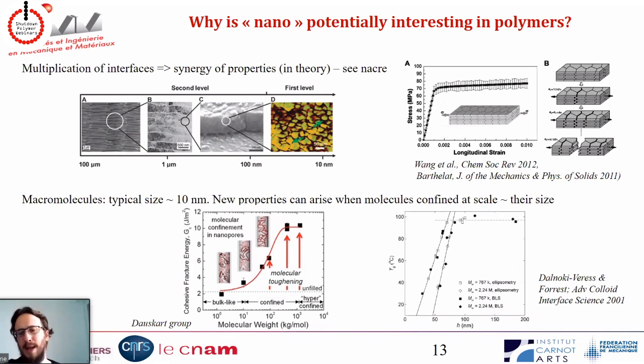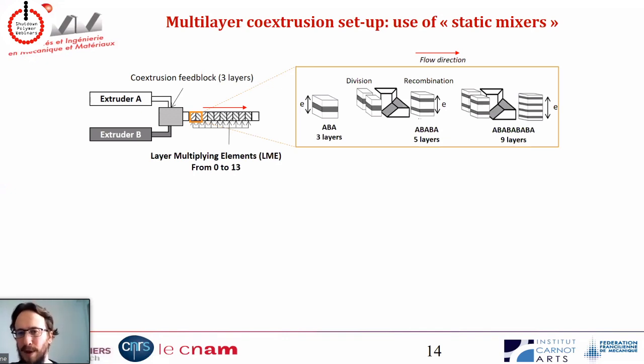nanostructures. And in the case of polymers, going to nano is even more interesting because it has been known for quite a while that polymers can display really new or interesting properties when they are confined at scales that are similar to their radius of gyration, say, so 20 or 50 nanometers. So people have seen that the glass transition temperature can be drastically modified. The mechanical properties can also be modified. So there can be some interest to try to go down to this nanoscale. So now I want to make these multi-layer films with 1,000 layers that each has nanometric thickness.